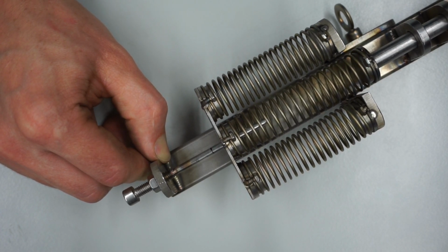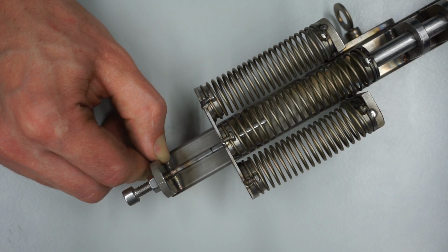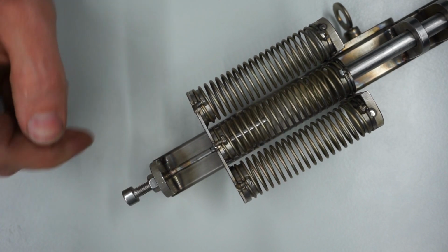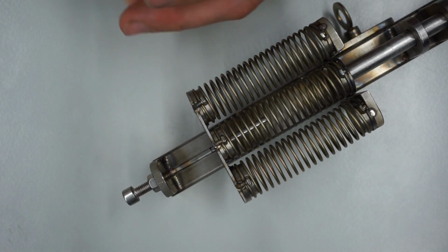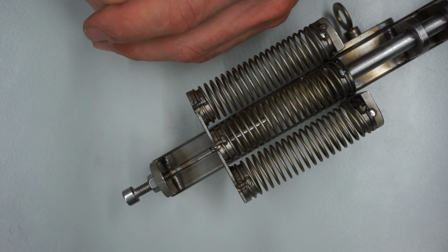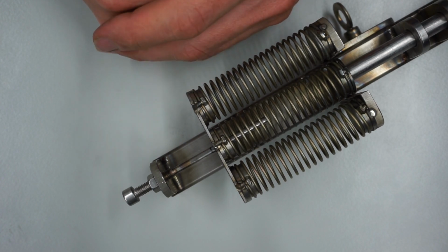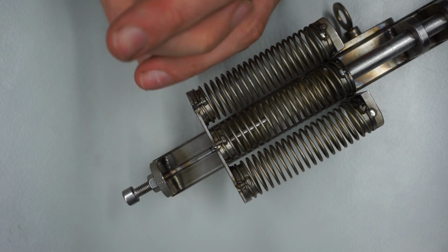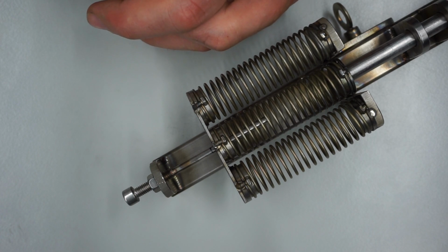So one thing very important to note here is that our workpiece has become shorter. This is one form of distortion and a natural result of the shortening of the central bar. Shortening of welded workpieces is a very common occurrence, particularly noticeable in cases of large or long structures with many welds, such as welded airplane fuselages or frames. Shortening can give quite some trouble with welding jigs, in which the workpieces get more and more stuck as welding progresses.